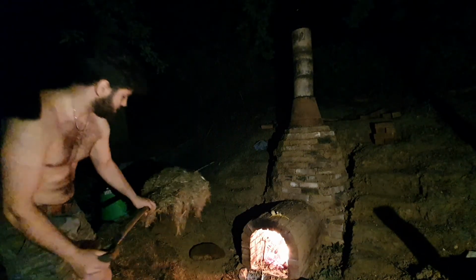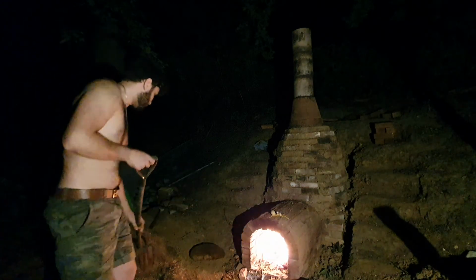Okay, so the kiln's been held at about 900 to 1000, and at some points I think I've got it higher, about 1200 degrees, which means the vessel now is ready for stage 2, which is reduction. So wet wood has been put in, and high carbon fuel, including whole green timber, which will burn slowly and produce a high amount of carbon. Now the next step is to take the grass, damp hay, you can see here, as that will spontaneously combust but also dampen and produce smoke, and limit the oxygen supply to produce a lot of smoke. Hopefully seal the carbon in the slip, fingers crossed.